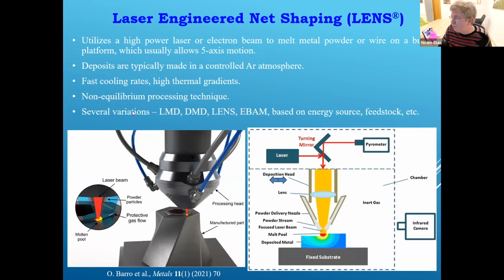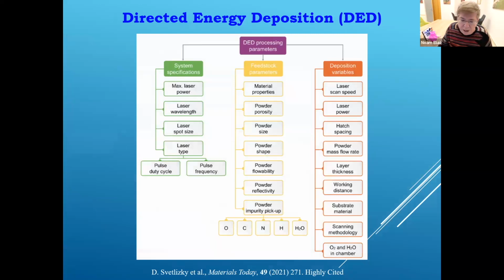Okay, this is a non-equilibrium processing technique, which also has to be recalled. If you look at which parameters are important, you can see here that there are a variety of parameters that can affect the outcome. Some of them are related to the specification of the system, for instance, the maximum laser power, which type of laser, the laser spot size, and so on. Some of them are related to the feedstock, the powder feedstock parameters, like powder size and powder shape. The flowability is very important.